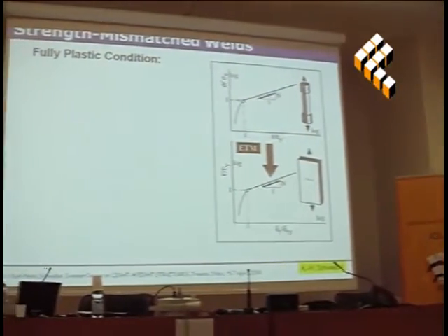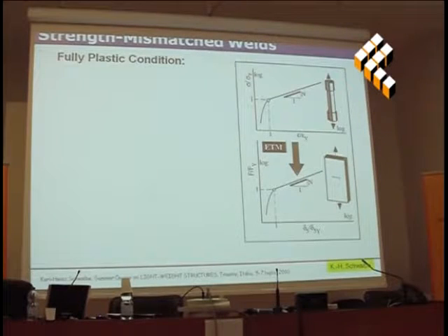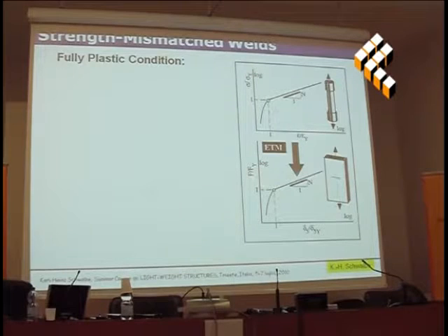Now, so this was the idea. Down here we are in the region of linear elastic fracture mechanics. I'm confident that I can deal with everything here up to the yield point using linear elastic fracture mechanics, including some plasticity correction. And so we can go up to this hinge point. It's kind of a hinge point, and from there on I can extrapolate into full plasticity, just using the straight line with the slope of n. That's the idea. That's all.